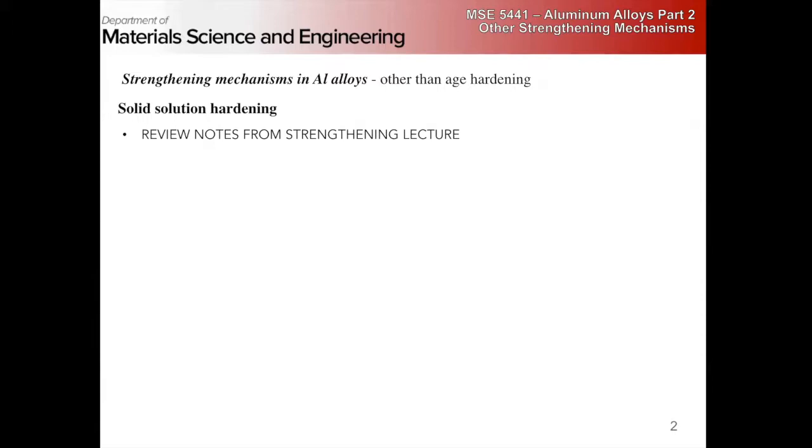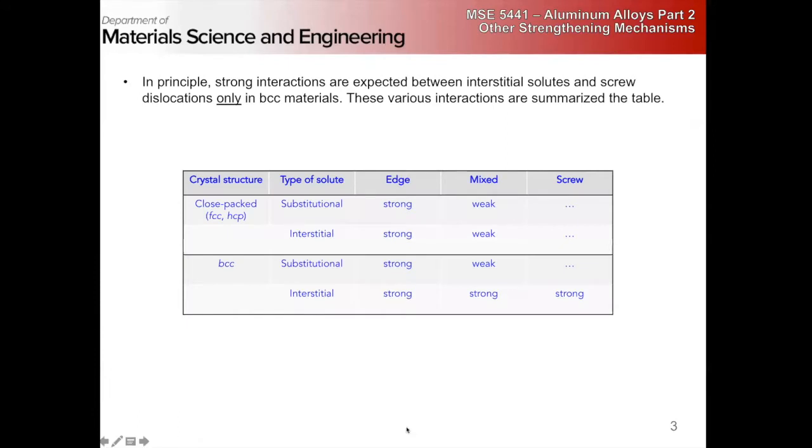So really the idea is we want alloying elements that have a big difference in size and a large difference in elastic stiffness, right? Big difference in relative shear modulus with aluminum on the more compliant side gives us the best. And we talked about spherical and tetragonal distortions.